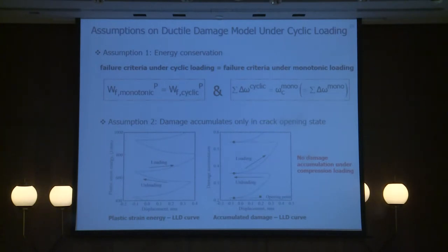The second assumption is that damage accumulates only in the crack opening state. To simulate this assumption, we modified our damage Fortran file to calculate damage accumulation only when the principal stress at the integration point is positive.